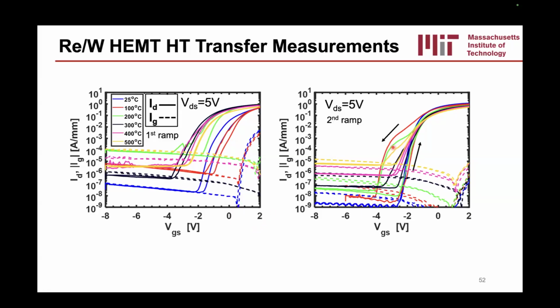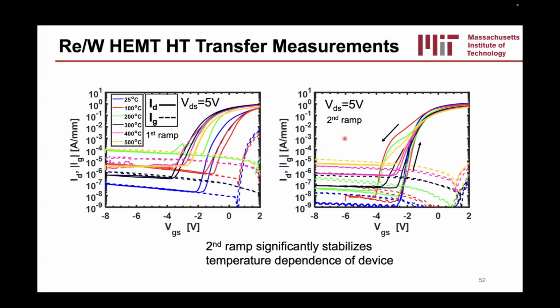It looks like the nitride passivation is struggling a little bit at very low temperatures, but once you increase the temperature, the detrapping rate is enough that electron trapping is not big, and so you don't get as much hysteresis there. And once again, the gate leakage does increase dramatically as you increase the temperature from 25 C to 500 C. All right, but the second round seems to significantly stabilize the device.